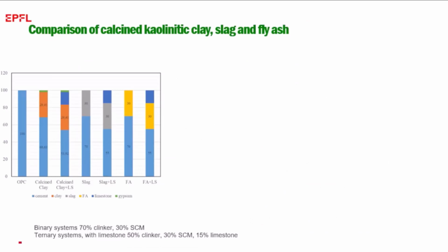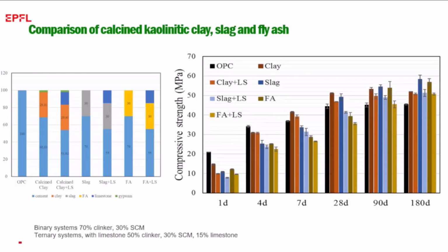Now, this is an interesting study we made where we compared calcined clay, slag, and fly ash, in binary blends with just 30%, and also in ternary blends where we have another 15% limestone. And if we look at the strength development here, we see that in the very long term, all these blends do very well.